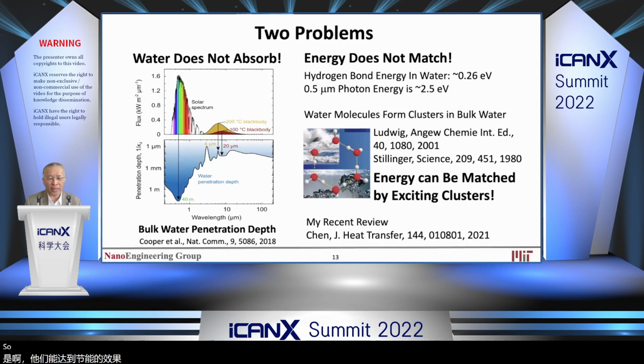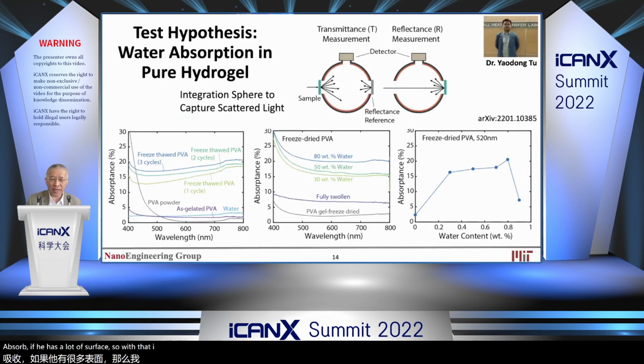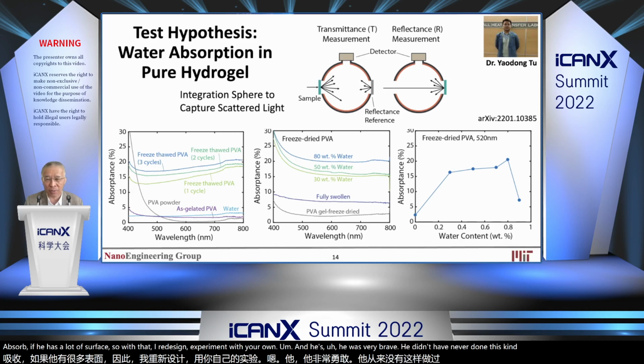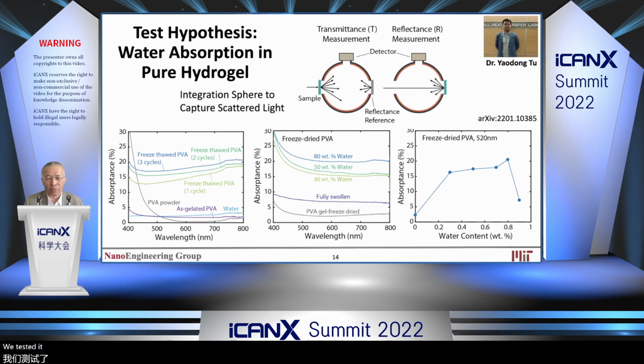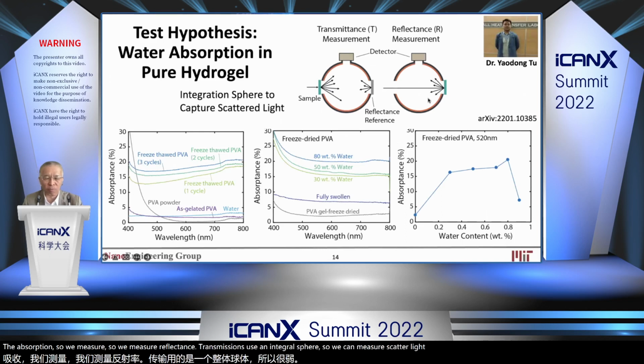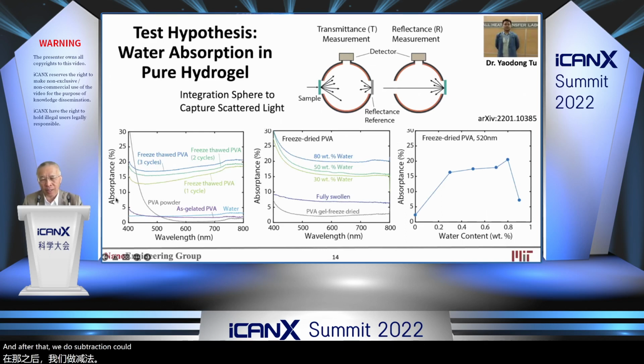So with that, let's say the question is, does PVA, polyvinyl alcohol, absorb if it has a lot of surface? I redesigned the experiment with Yaodong, and he was very brave. He had never done that kind of experiment before. So we tested water absorption in pure hydrogel. You can see on the left, the gelated polyvinyl alcohol and water, the absorptance we measure. We measure reflectance and transmittance using an integrating sphere, so we can measure scattered light also. And after that, we do subtraction to get absorptance.